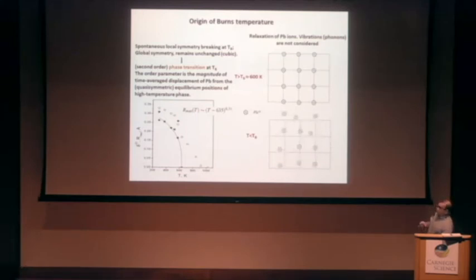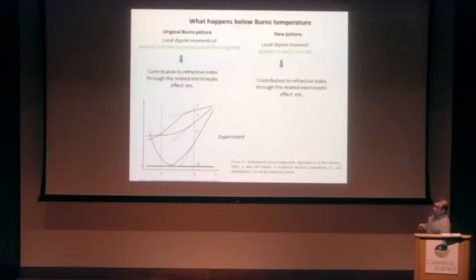And the change of properties observed experimentally at this Burns temperature could be explained in the following way. You know that the original Burns picture is that at Burns temperature, polar nanoregions appear. This means that the dynamic dipole moments of different unit cells become ordered in some nanoregions, and this leads to an anomaly in the temperature dependence of the refractive index due to the electro-optic effect.